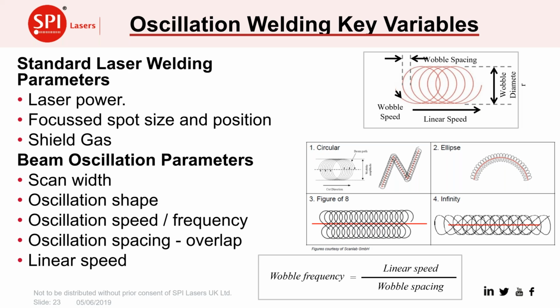Generally, the circular pattern is the first choice. Partly this is for practical reasons: if we're welding shapes which aren't always linear, not just welding in a straight line, the circular pattern is independent of the direction of travel of the linear speed. So we can use it as we weld round corners on packages, for instance.